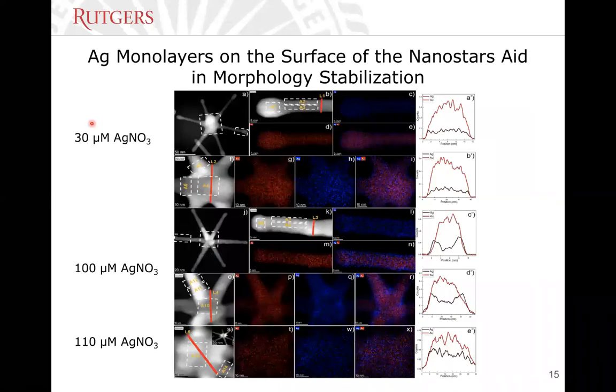What if we then did some STEM EDX analysis? What we observed is that we can identify where the metallic silver goes on the stabilized nanoparticles. And you see here that at very low concentrations of silver nitrate, it basically deposits primarily as a bare monolayer on the surface of the spikes. But if you start increasing the amount of silver, we see that this monolayer becomes more and more uniform. And then if we go to the maximum amounts of silver nitrate, we see that this silver migrates down into the crevices among the tips, and that's where it settles.